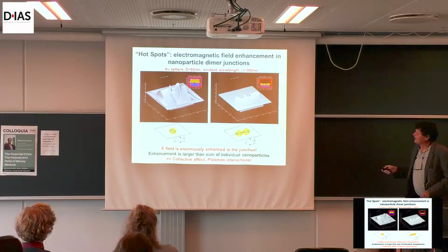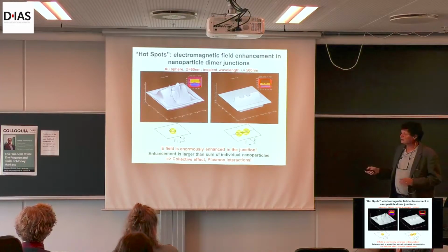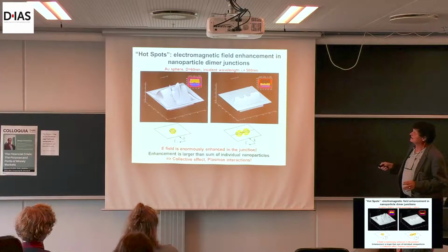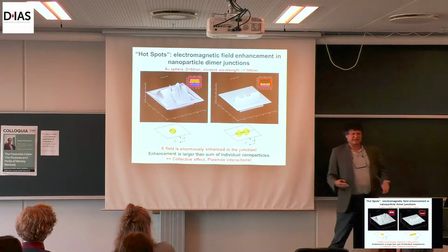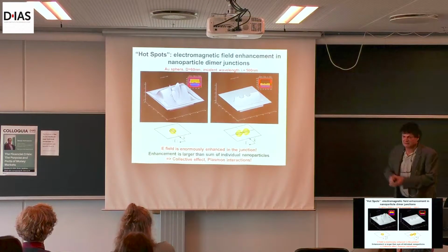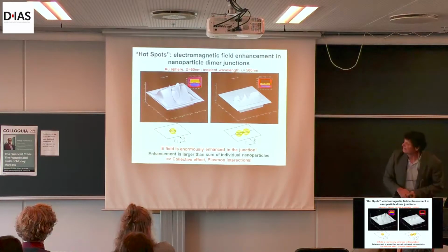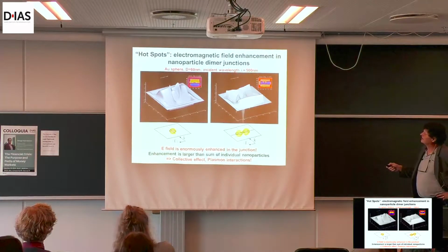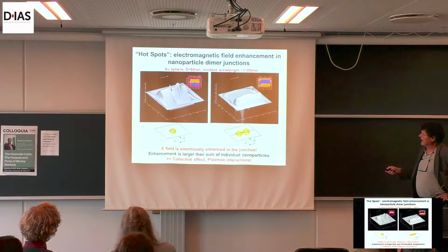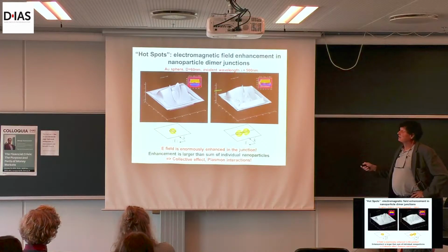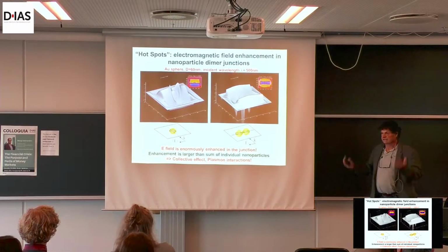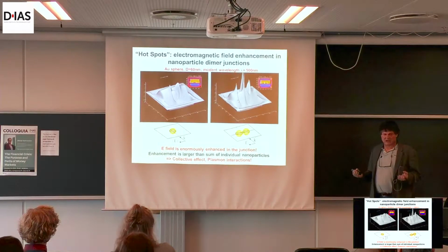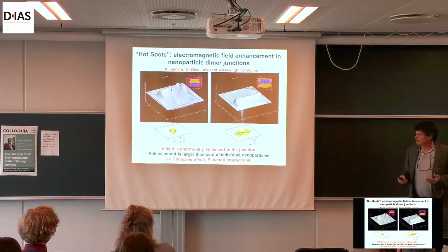Let's see now when we have 2 nanoparticles, same spheres, same wavelength. Let's see what happens. Normally we think about 2 laser beams that will be twice as intense, but let's see what happens when we look. When we have these 2 nanoparticles next to each other, we get an enormous amplification of the intensity in this gap. This amplification is about 100. Here it was about 10. So we don't get 20 here as we would have assumed with superposition. No, we get 100. So something fundamentally happens, and that is that the plasmons start to interact.